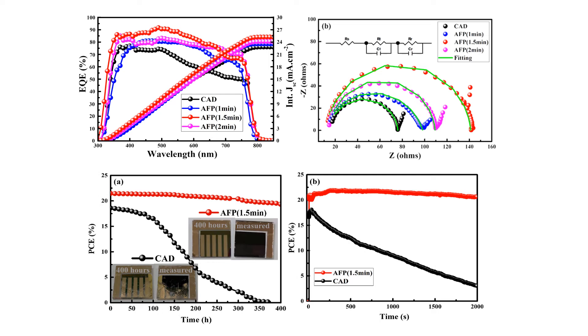We also calculated the external quantum efficiency of the devices. The quantum efficiency of the anti-solvent fumigation process devices was higher than the CAD devices, showing that we can more effectively convert incoming photons to charge generation and collect them at the corresponding interfaces.